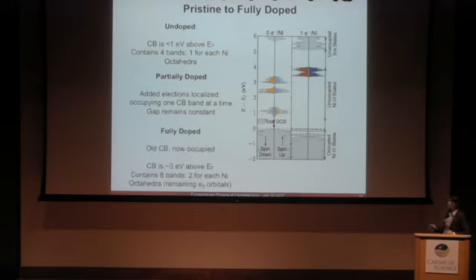Finally, when we fully dope it, our old conduction band is completely occupied. It's moved into the valence band, and our new conduction band is really about 3 eV above the Fermi energy. And so what's happened is we've rearranged the bands and opened a new gap that gives us this very insulating state.